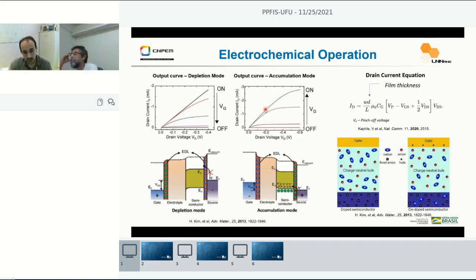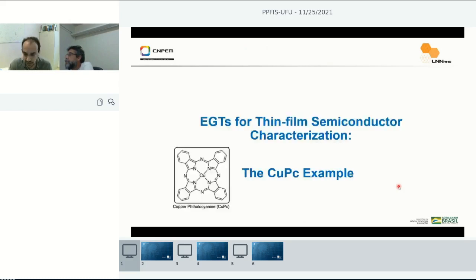Or, depending on the material, you can have an accumulation mode, which means that by increasing the gate voltage, the current increases because you dope your semiconductor with these electrolyte ions. I want to bring your attention to the current equation, which contains the film thickness, which means that if your current depends on the film thickness, you have an electrochemical operation mode. Here there are two pictures that show the device before polarization of the gate and after a positive polarization of the gate, showing that anions accumulate at the gate interface, while cations enter the semiconductor film and may dope or de-dope it, depending on the material.